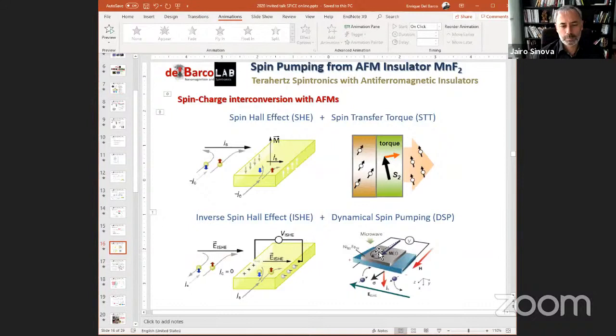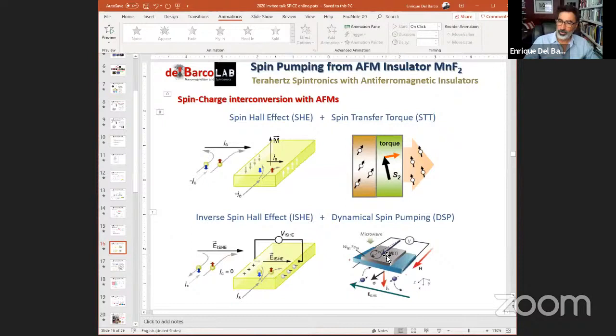And in every cycle of precession, there is a spin angular momentum, a quantum, that can be taken by conduction electrons in platinum, in a way that one conduction electron in platinum will go into the interface with a given polarization direction and the other one away with the opposite. So there won't be any net charge current perpendicular to the interface, but only spin current. The spin current is going to be diffused. It's going to decay as we move away. And that spin current is going to be converted in platinum, because of the high spin orbit coupling in platinum, by means of this inverse spin Hall effect into a charge current laterally that we can detect by applying two wires at the two ends of the sample.